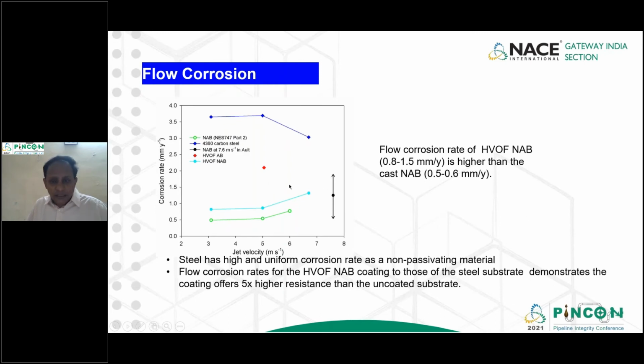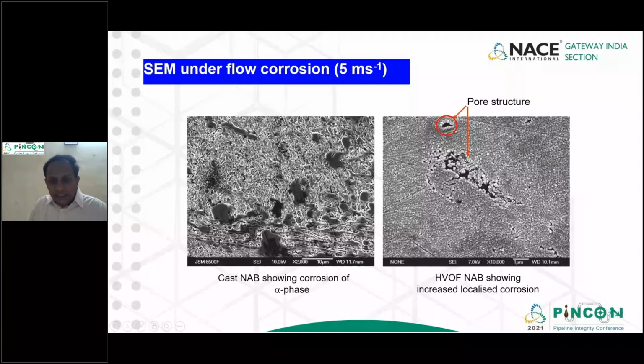This was actually, as we also confirmed with the literature, that the flow corrosion rate is a little bit higher in the case of a coating compared to the cast. It was like 0.8 to 1.5 millimeter per year, then for the cast NAB, 0.5 to 0.6 millimeter per year. Then we go to another image, the SEM. You could see that the coating had a lot of attack in the pores, and the electrolyte was able to penetrate and create localized corrosion.